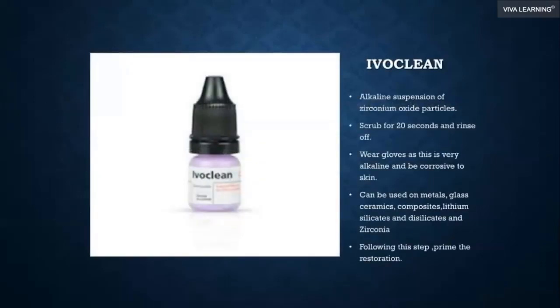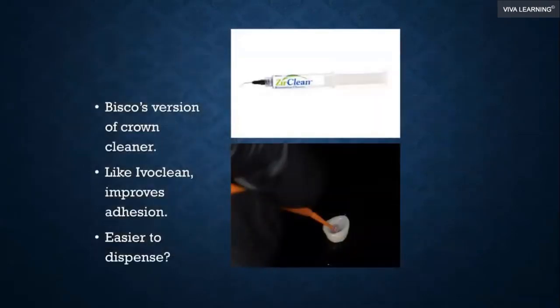The traditional one that many have used is a product from Ivoclar called Ivoclean. Ivoclean is an alkaline suspension of zirconium oxide particles. First of all, shake the bottle, because the particles settle at the bottom. Dispense some in the crown, scrub it for 20 seconds and rinse off. After you rinse this off, you're able to place your primer and you're ready to bond your tooth into place. Ivoclean can be used both on lithium disilicate as well as zirconia.